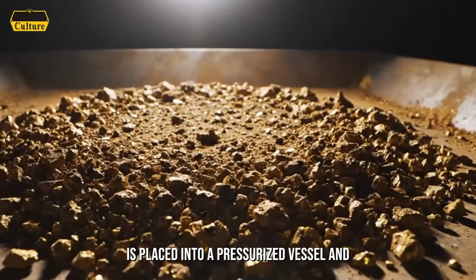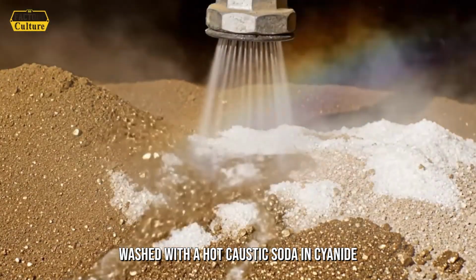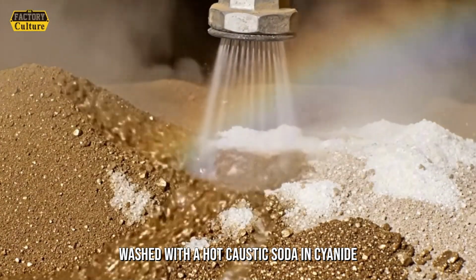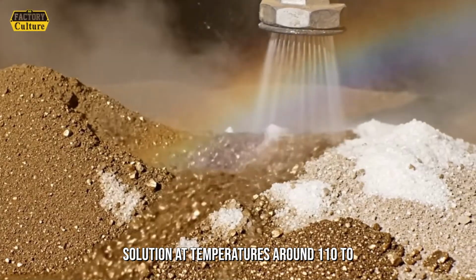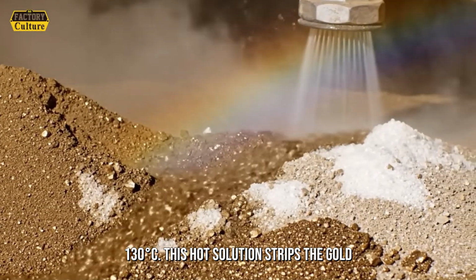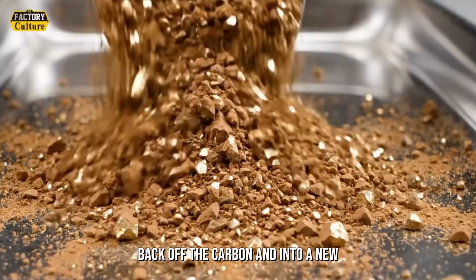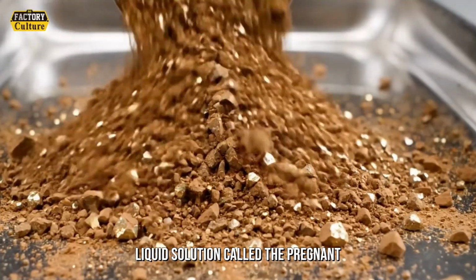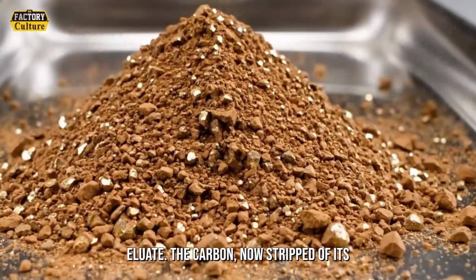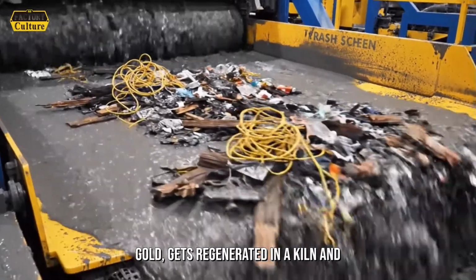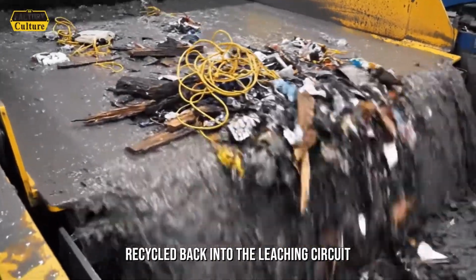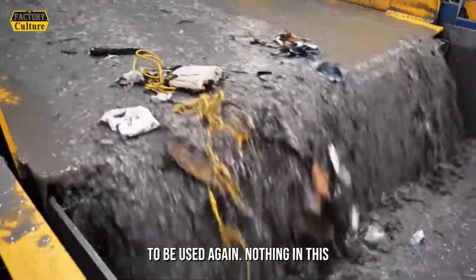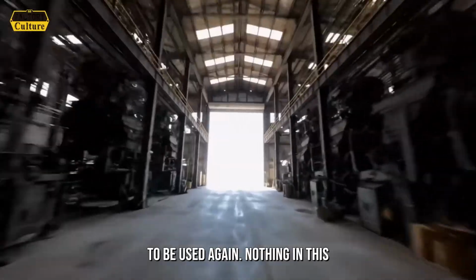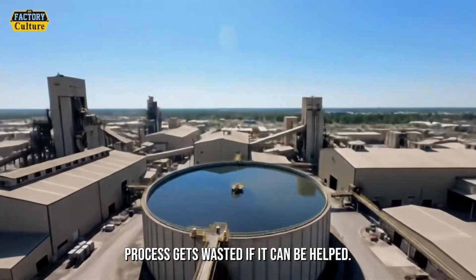The carbon is placed into a pressurized vessel and washed with a hot caustic soda and cyanide solution at temperatures around 110 to 130 degrees Celsius. This hot solution strips the gold back off the carbon and into a new liquid solution called the pregnant eluate. The carbon, now stripped of its gold, gets regenerated in a kiln and recycled back into the leaching circuit to be used again. Nothing in this process gets wasted if it can be helped.